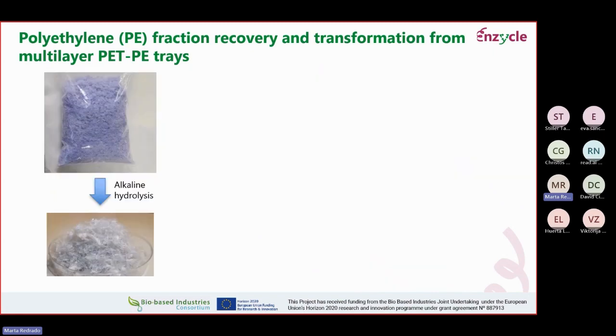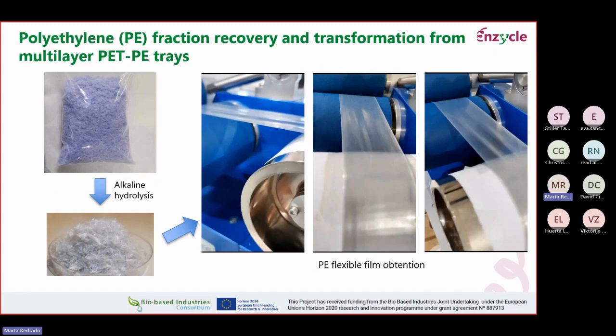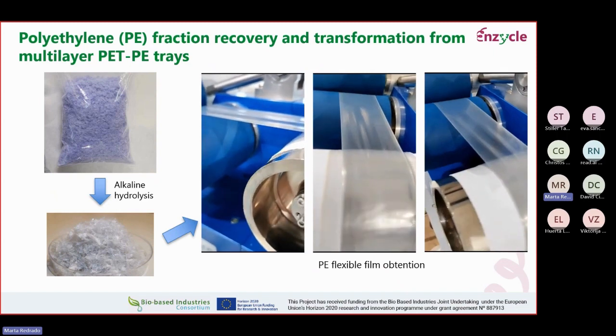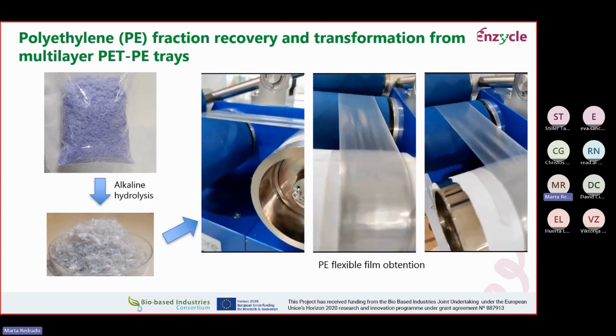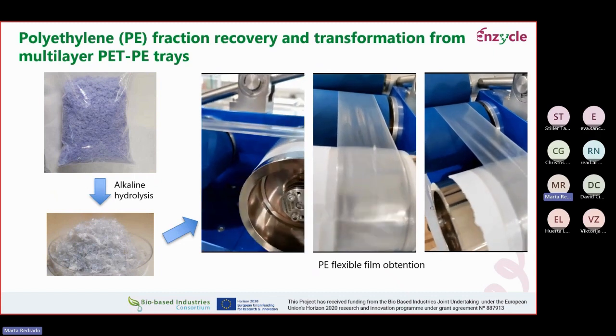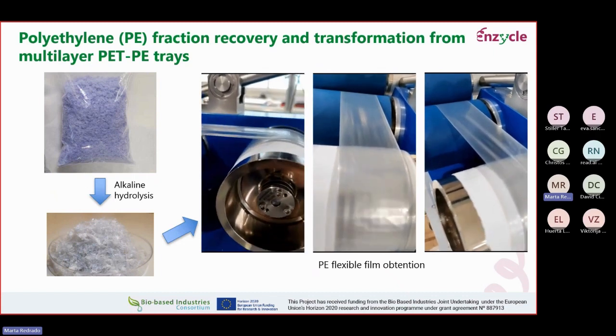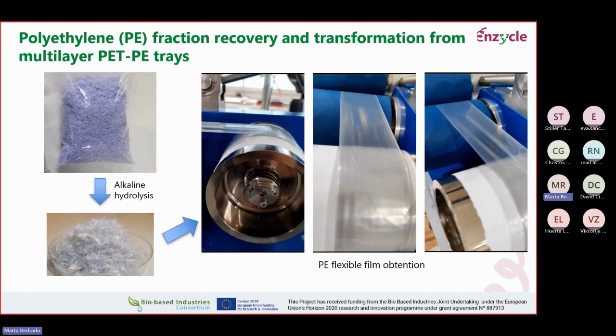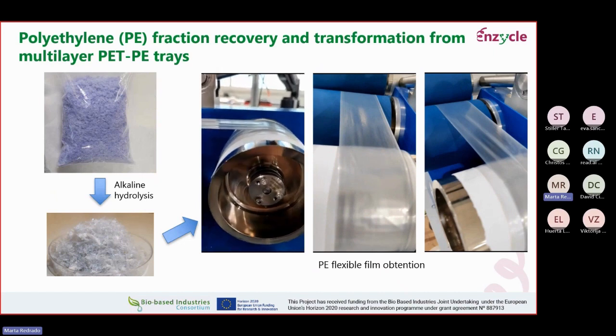So what we decided was to perform an alkaline hydrolysis of the polyethylene residue to eliminate this small amount of PET that was still present there. So we managed to obtain a clean polyethylene material, which in the end was indeed suitable to produce nice thin polyethylene films, which is a very nice result. As you see, the film is transparent, so it also has quite good physical and mechanical properties. So we are pretty satisfied.